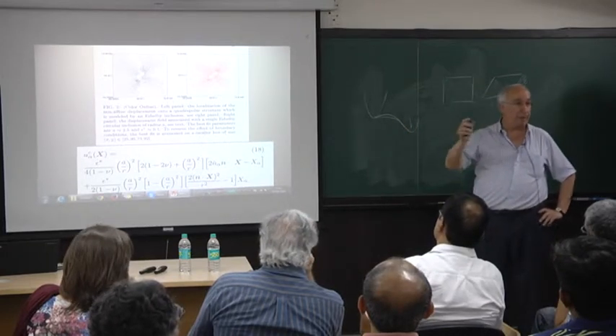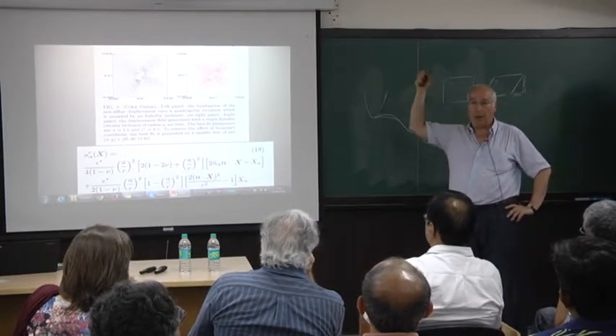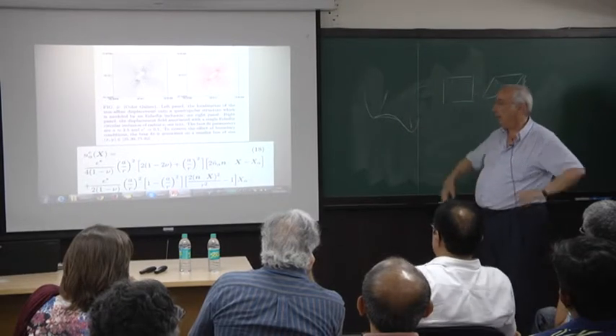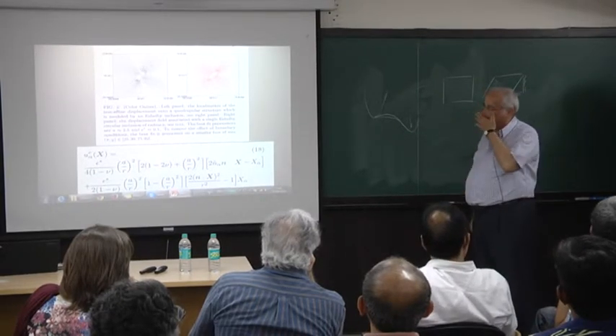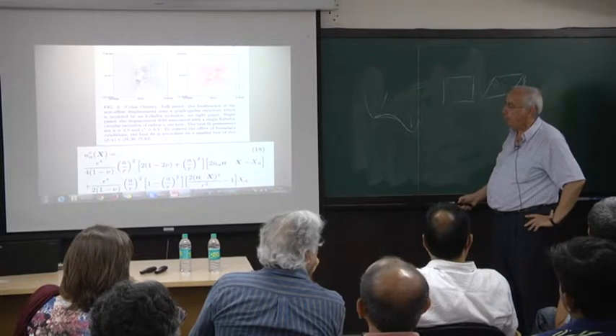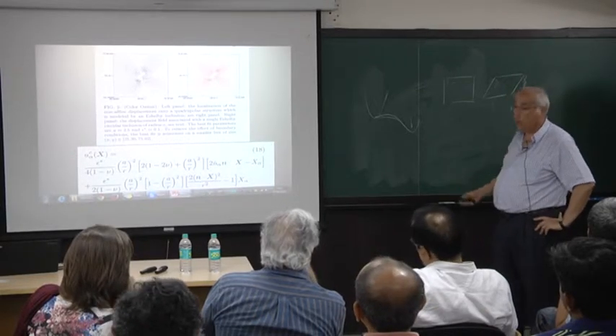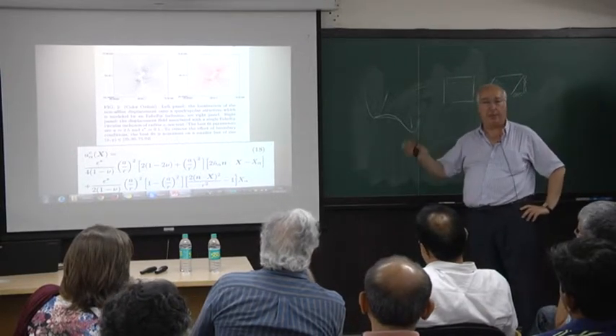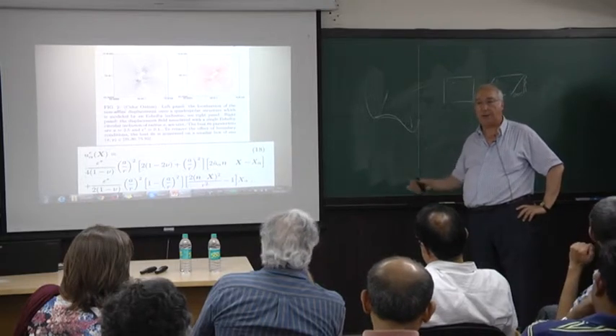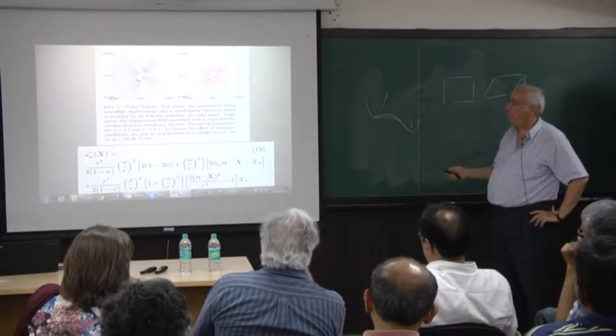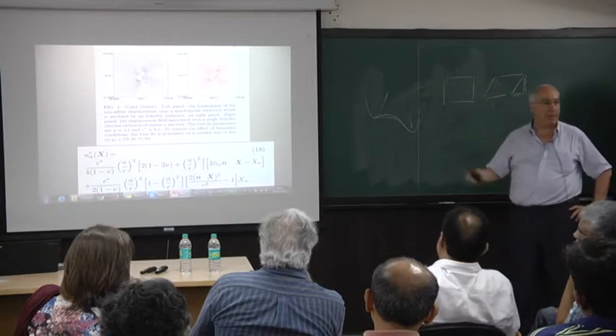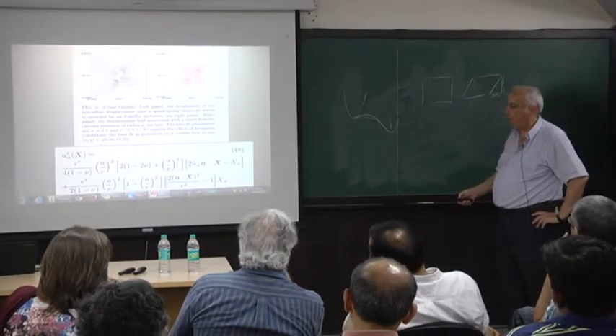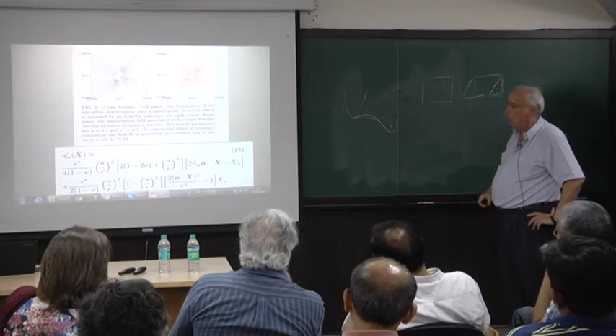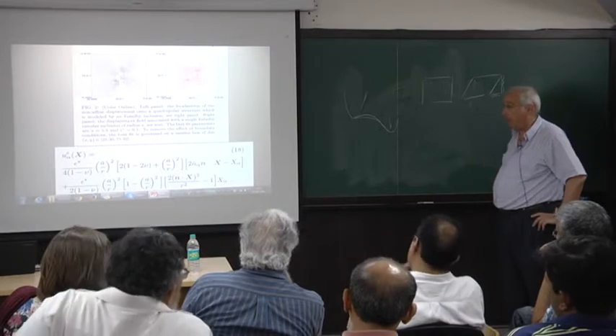You take a different system, you change the Lennard-Jones, you go, I don't know, to another situation, you get a different epsilon star and a different A, but the solution is universal. That is to say, this is indeed the cheapest way to release stress. So you have a non-affine eigenfunction with eigenvalue going to zero always, but you only change the two parameters here, epsilon and A.